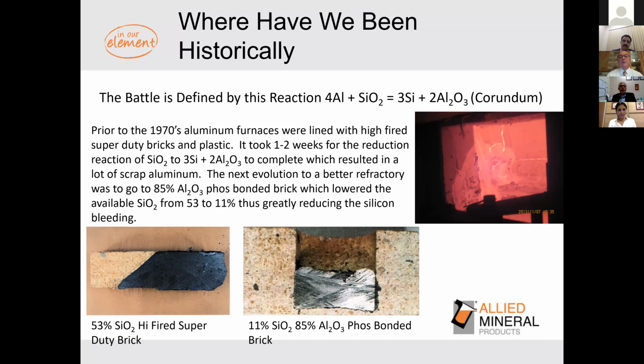So historically, what the aluminum manufacturers had to do is put in the high fired super duty, and it was high fired because it lowered the porosity. But what they got is what they call silicon bleeding into the aluminum through the reduction reaction. You can see here with the high fired super duty that, based upon the thermal profile through the refractory lining, it followed that thermal profile as far back as it could maintain liquid aluminum to reduce the silica in the refractory. It dumped high percentages of silicon. And I guess, as long as you were making die-cast alloys, not so bad. But if you're making 5,000 series, 3,000 series, 7,000 series, high silicon was very bad for the alloy.